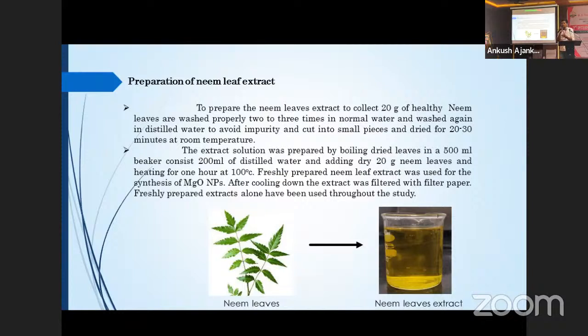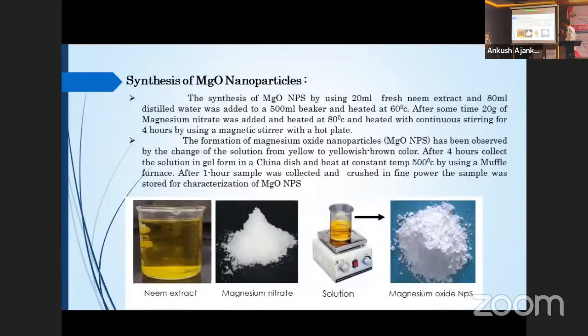This avoids loose impurities. Second, the extract solution was prepared by boiling the leaves in a 500 ml beaker with 200 ml of distilled water, adding the 20 grams of neem leaves and heating at 100 degrees Celsius for 1 hour. After 1 hour, cool the solution down and filter it using filter paper. Next, the synthesis of magnesium oxide nanoparticles.